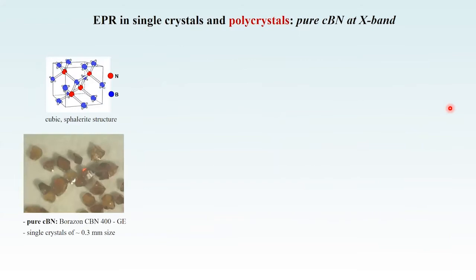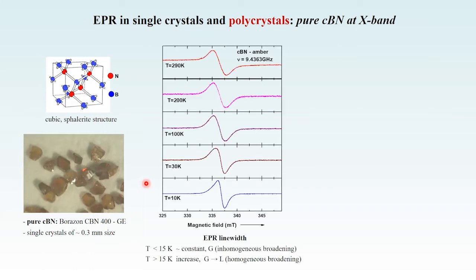Now we see what happens when we measure a collection of small single crystals. These are pure cubic boron nitride single crystals, but they are not colorless — they have a nice amber color. We expect there to be a color center or an impurity detectable by EPR. One single crystal has too small a volume to be measured in X-band. Adding several crystals in the sample tube, we observe a polycrystalline EPR spectrum, which is a broad line.